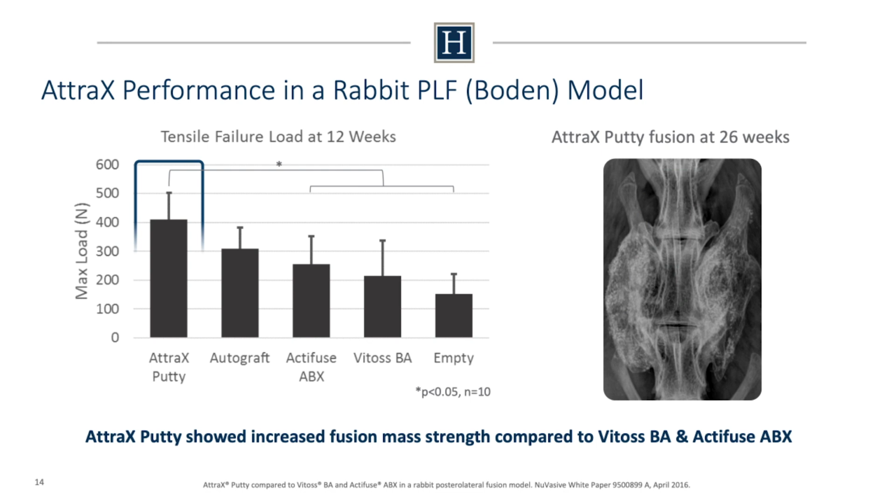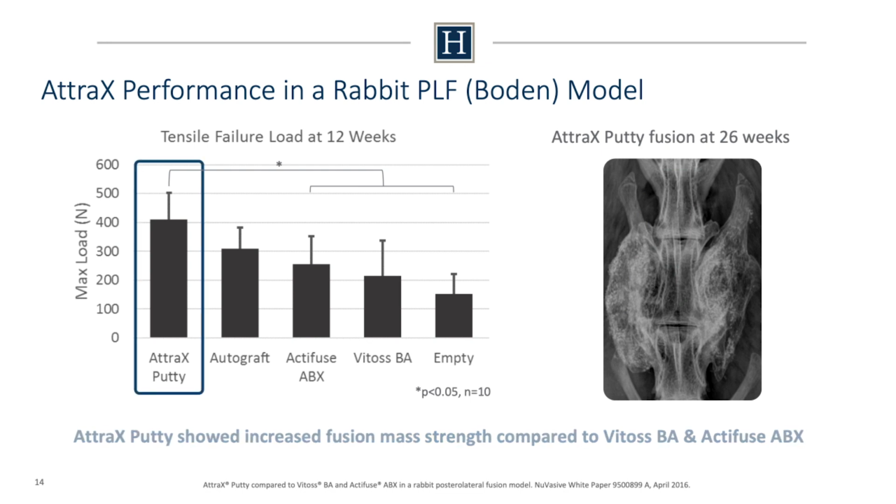From the same study, the tensile failure load of the fused specimens was assessed at 12 weeks. Attrax Putty showed increased fusion mass strength compared to traditional ceramic scaffolds and autograft. On the right, you can see incorporation of the ceramic granules into a trabeculated transverse process fusion mass.